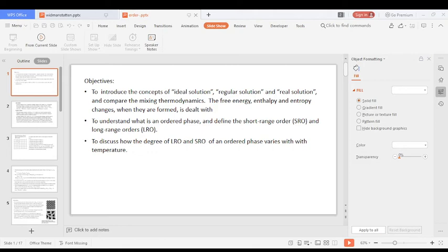An example of an ordered phase is BCC beta brass occurring below 460 degrees centigrade. It is called the L20 or B2 superlattice. The BCC or so-called A2 lattice can be considered as 2 interpenetrating simple cubic lattices, one containing the corners of the BCC itself, the other containing the body centering sites. If these 2 sublattices are denoted as A and B, then the formation of a perfectly ordered beta superlattice involves segregation of all copper atoms to the A sublattice, zinc to the B sublattice.